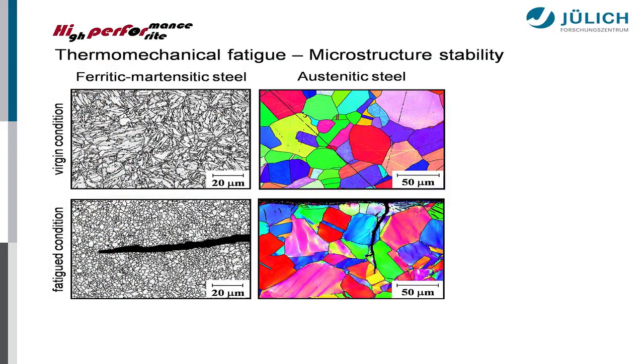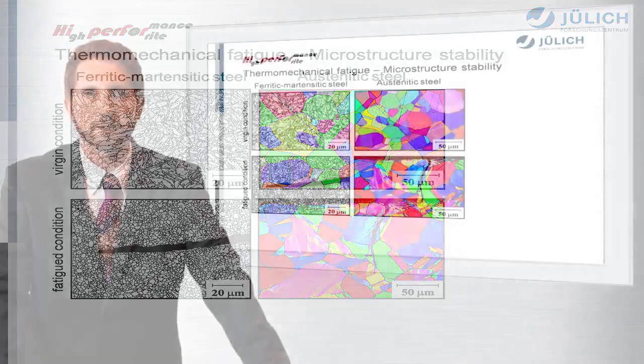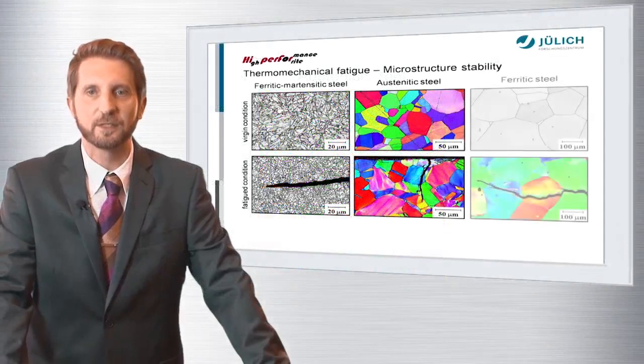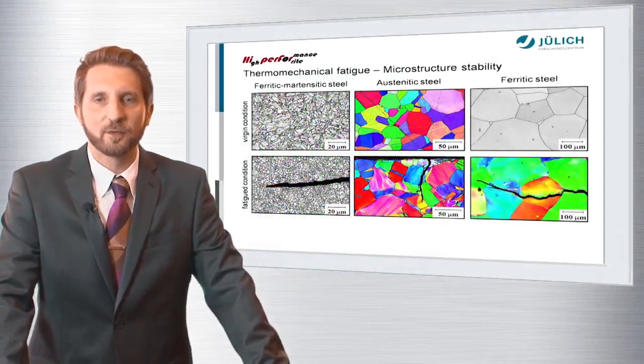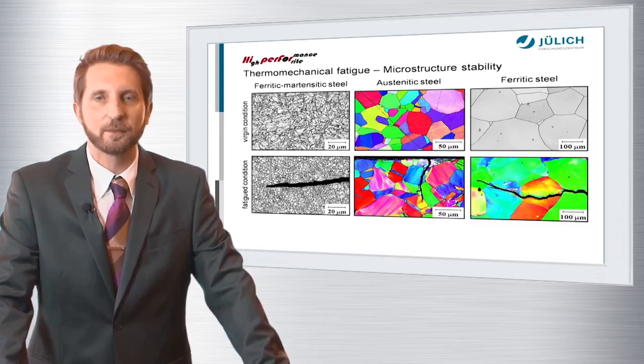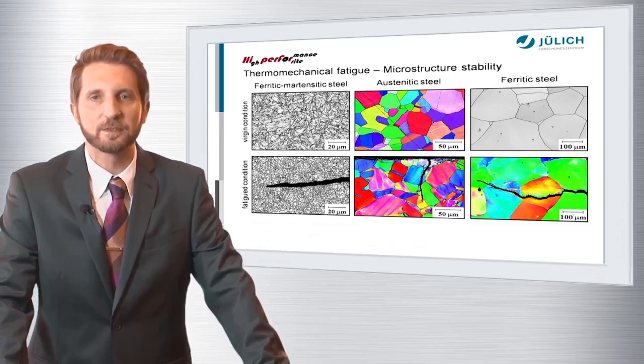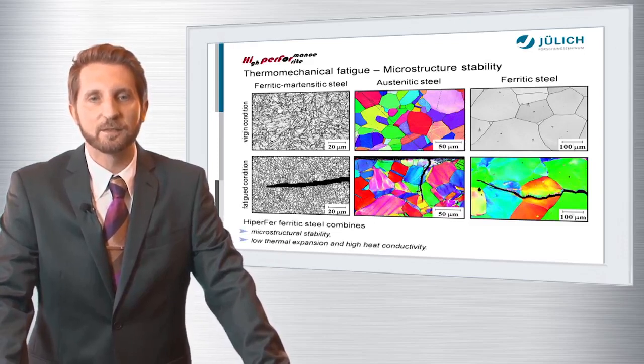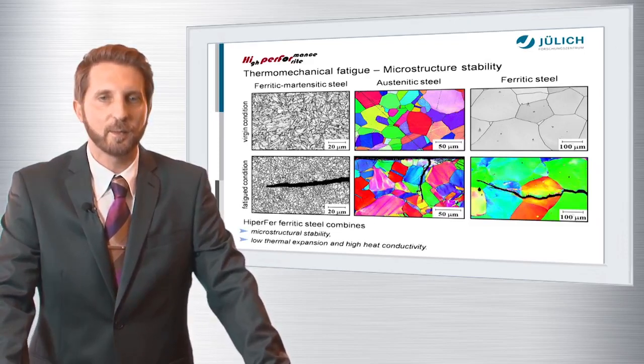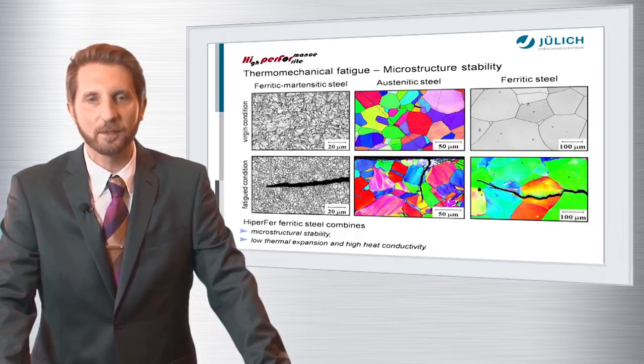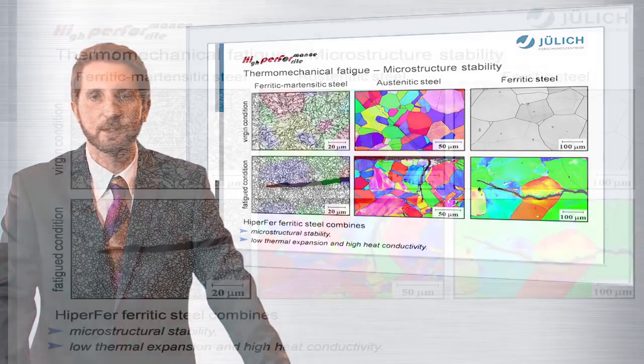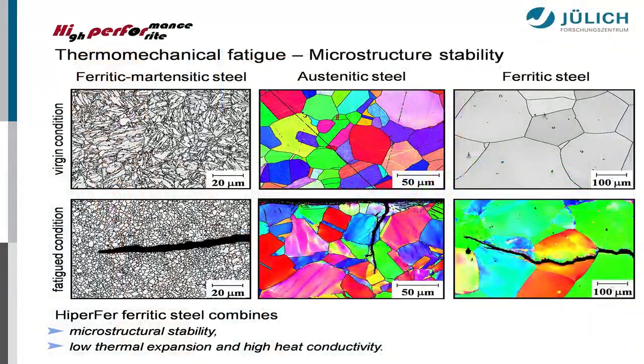The premature failure is more or less owed to the comparatively high thermal expansion coefficient of these materials, and that means that the amount of plastic strain energy per cycle is much higher than for the ferritic martensitic and the ferritic steel. In case of the ferritic materials, microstructure remains stable too, so we don't suffer any recrystallization. And to summarize this, we can say that our HiperFer ferritic steels combine microstructural stability, low thermal expansion, and high heat conductivity, and this is very beneficial. And for this reason, they reach the longest lifetime in thermomechanical fatigue loading.